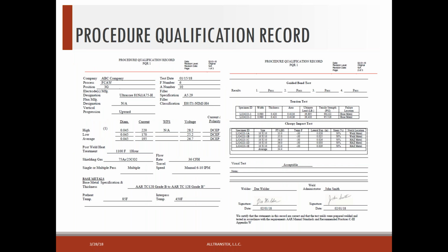Okay, an example of a procedure qualification record, and what would be in here is the results of our tensile test, the results of our bend tests, our corrosion tests, and then we would have notch toughness values specified here, and who welded the coupon, that sort of thing, where it was tested. So this is an example of a PQR, procedure qualification record.